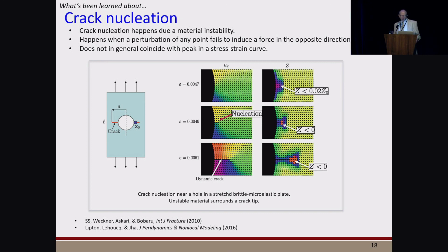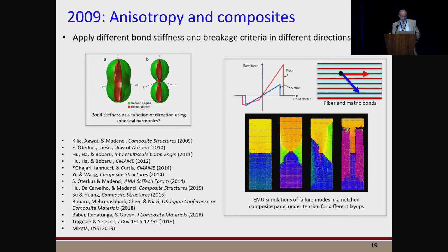Now, at the beginning, I referred to this mysterious process by which cracks appear and grow. What we've learned a lot about in the past 20 years regarding crack nucleation is that in peridynamics, it can be viewed as a type of material instability in which, when bonds start exceeding the maximum in their force versus extension relation, in effect, the wave speeds become imaginary, resulting in a type of material instability that results in the nucleation of a crack. And this same instability exists as the crack grows ahead of the crack tip.